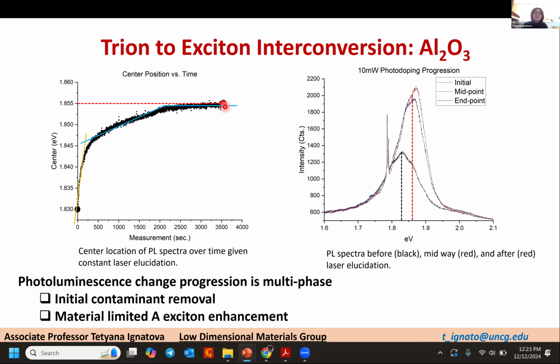We did not present it here, but after this period of time, we started to see a slight decrease of photoluminescence. And on the right side, you can see how the spectral lines look. At the beginning, so after illumination, at the middle point somewhere here, you see that the intensity of photoluminescence jumped up almost twice, and we see a significant shift of the maximum of the photoluminescence line.